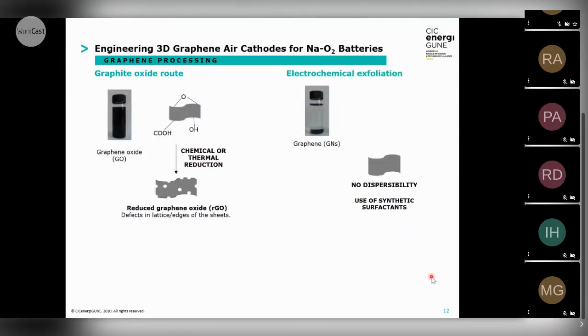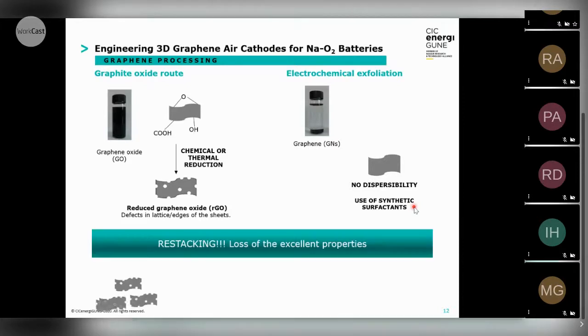When we are looking at processing, it's really important because these two methods are going to process in a different way. In the case of graphite oxide, it's really easy, for example, to have a suspension in water, but then we have the problem of all these functional groups on the surface. So it requires a post-synthesis chemical or thermal reduction in order to get the defect sites on the sheets of the graphene. In the case of the electrochemical exfoliation, we cannot disperse the graphene, as you can see here with the water, and there is the drawback of the need of using synthetic surfactants.